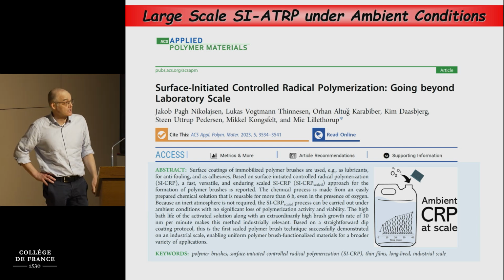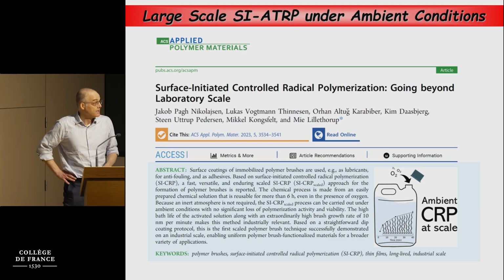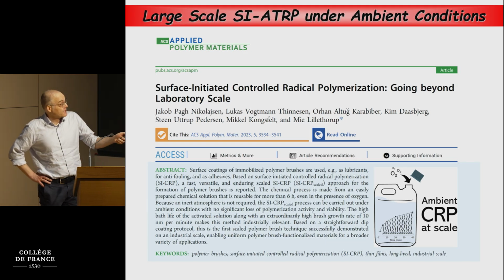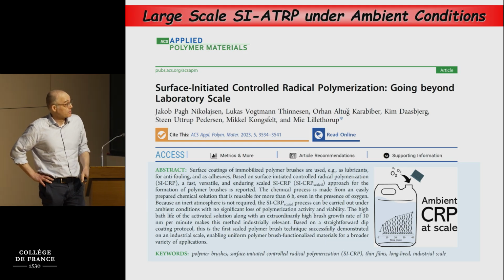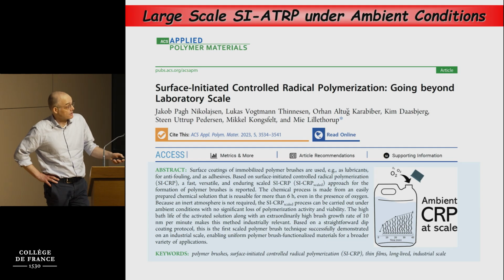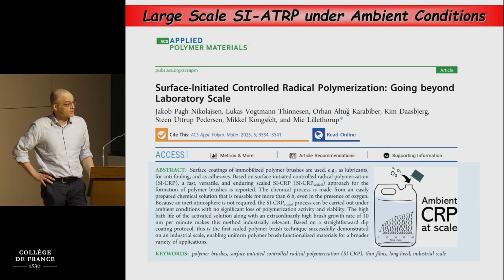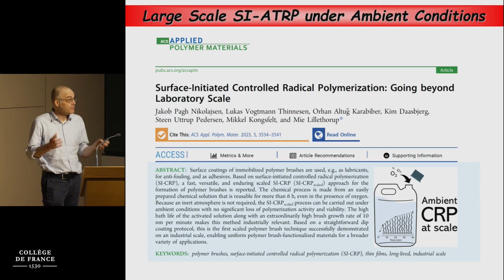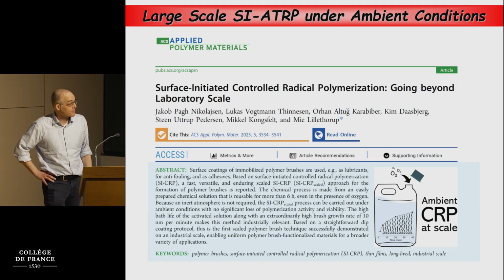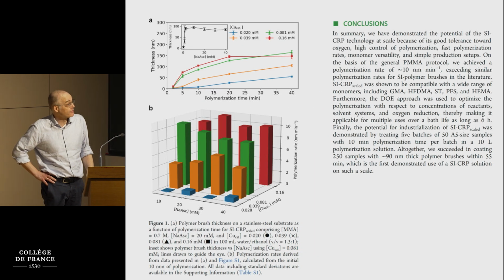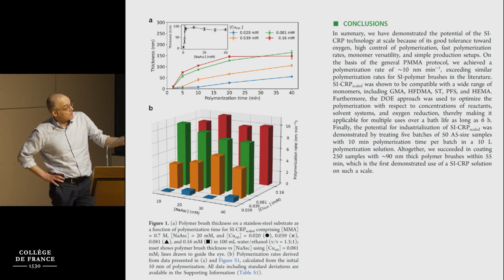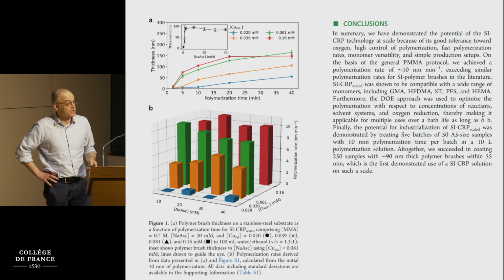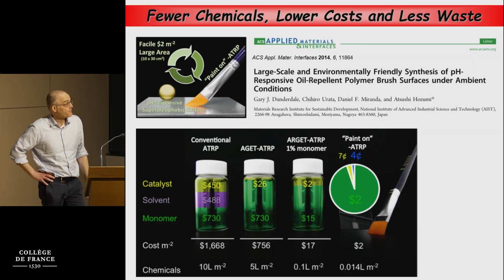And I just picked 3 examples of papers, not from our own group, to make this point. This is a nice paper from a group in Aarhus that was published a couple of years ago, where they show they can coat up to 50 A4 size steel metal plates under ambient conditions via controlled radical polymerization in a very effective way, very reproducibly, within half an hour. And this reaction mixture is basically usable over 6 hours.